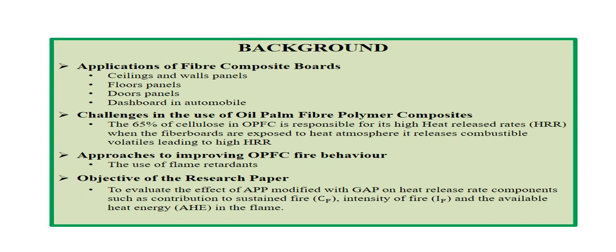The high heat release rate can be reduced by the addition of flame retardants during processing. Many researchers suggest that aluminum trihydroxide and ammonium polyphosphate are suitable to achieve a reduced heat release rate. Now, the main objective of this research paper is to evaluate the effects of ammonium polyphosphate modification with gum arabic powder on the heat release rate of oil palm fiber.